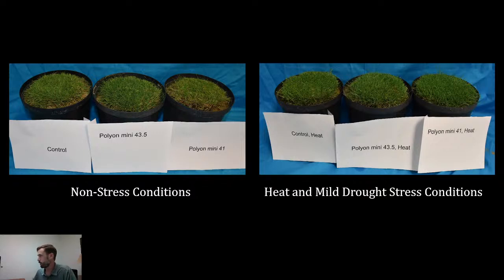So here on the left, the photograph on the left, you have the non-stress conditions. So these are the 72-degree day, 65-degree night temperature conditions, well-watered conditions. And you actually know that the 41 mini, the release is actually pretty slow under these conditions. So you're not getting the ideal greening response that you would want to see. A bit better greening response with 43.5 mini. So again, a thinner coating is going to release quicker under these cooler conditions.